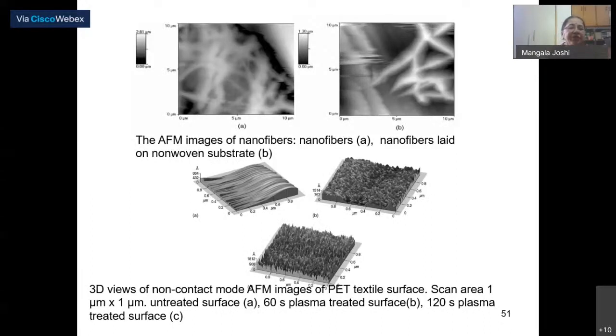So here I am showing you the AFM images, how we can use AFM to do our characterization of samples. So on the top, you can see the AFM images of nanofibers, and this is just the nanofibers, and here you can see nanofibers laid on non-woven. So the bigger diameter fibers are the micron size non-woven on which nanofibers have been deposited. So AFM can be used, although SEM seems to be a much better technique, but AFM can also be used. In the below figure, these are the 3D view images of non-contact mode AFM images. Now, what we have done is, we have taken a PET fabric, a PET textile surface, and we have given it a plasma treatment.